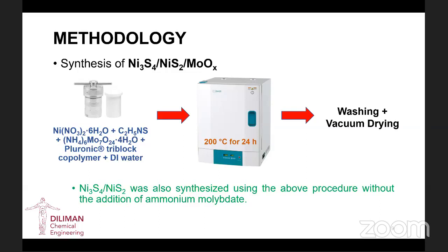And then the material without molybdenum oxide was also synthesized using the same procedure, but without the addition of ammonium molybdate.